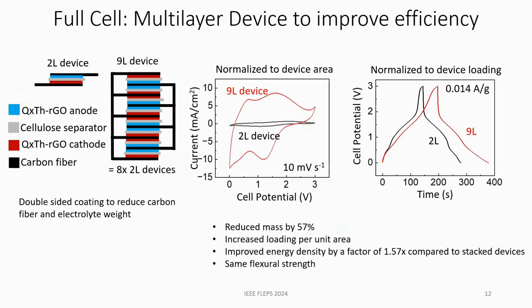Another thing we did to improve the efficiency is to make multi-layered devices. So most of the device weight is made up of these carbon fiber substrates. So besides the active area, it's just additional weight. So what we did is we coated both sides of the substrates to make double-sided electrodes and then stacked them together and made our full cell. So this 9-layer device would be worth 8 2-layer devices, but it uses less carbon fibers and electrolyte overall. And it reduces the mass by 57% compared to the individual devices.